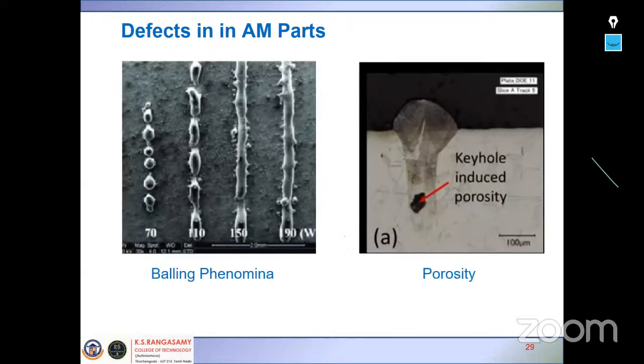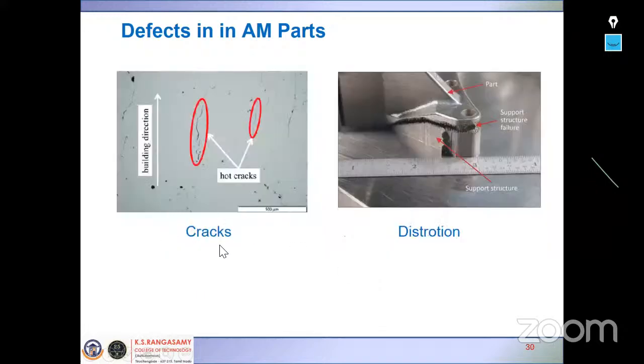So I will show some of the challenges and defects in additive manufactured parts. The balling phenomenon: the under layer may not be properly wetted, and then you will face balling on the surface. Porosity is another defect in the part, and then the cracks which form during 3D printing. This is the build direction. You see the hot cracks present in the material. This is because of the thermal gradient. Due to the thermal gradient, residual stresses are present in the material, and that will lead to cracks in the 3D printed material.